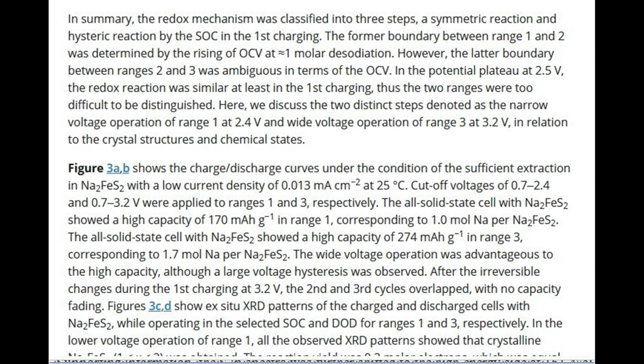In summary, the redox mechanism was classified into 3 steps: a symmetric reaction and hysteretic reaction by the state of charge in the first charging. The former boundary between range 1 and 2 was determined by the rising of OCV at 1 molar desodiation. However, the latter boundary between ranges 2 and 3 was ambiguous in terms of the OCV.